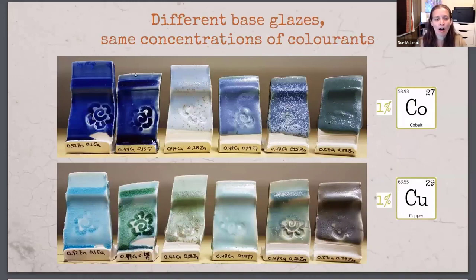Now, these are all different base glazes, but with the same concentrations of colorants above and below each other. So these two are the same base glaze with 1% cobalt, 1% copper. These two are the same base glaze. Again, all of these have 1% cobalt and all of these have 1% copper. So you can see, depending on the base glaze that you add your 1% of cobalt or copper to, you can get very different results.